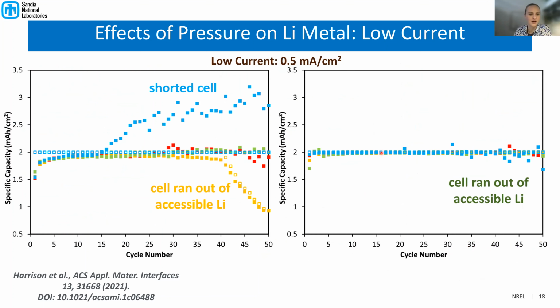Now, of course, if you're comparing just the cycle number and the ways that these electrodes fail, you can see that some of them at no pressure over here would short very quickly, and then some would run out of accessible lithium, whereas at higher pressure, it would just run out of accessible lithium after some time. And so we knew that the failure mechanisms were a bit different between the low pressure and the higher pressure case. Now, we had a hard time imaging lithium.